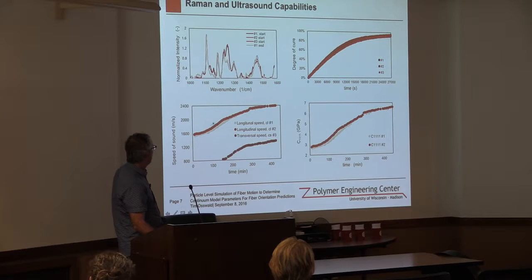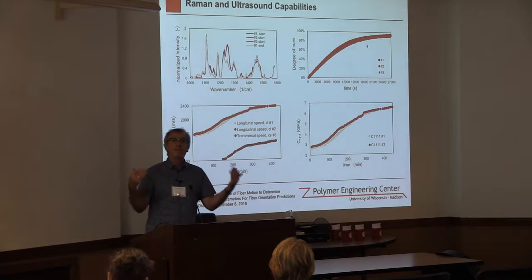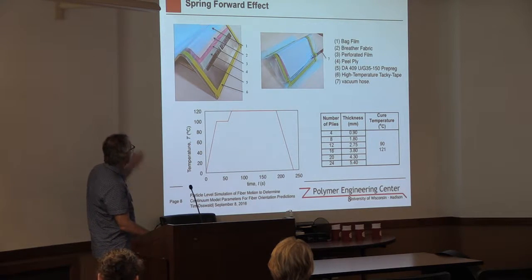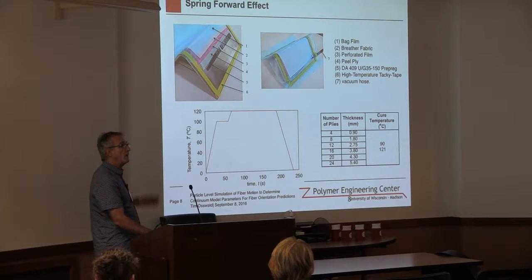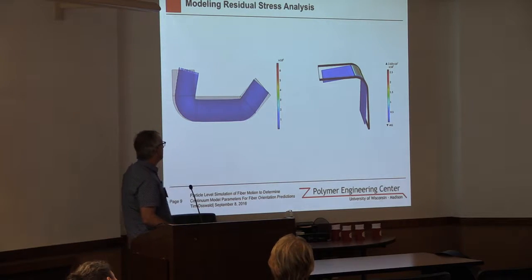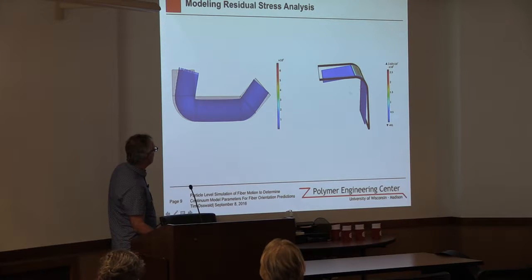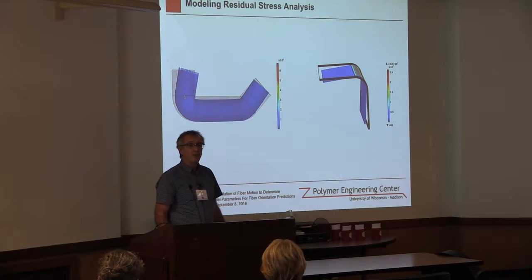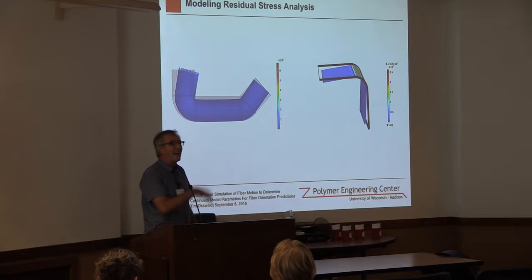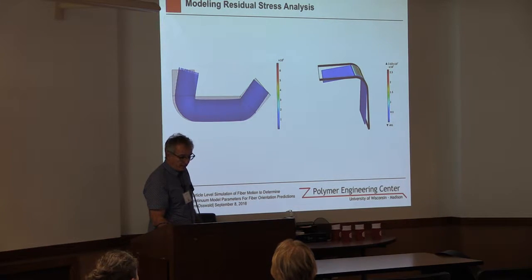On the other hand, the speed of sound also increases in time, so we can relate the modulus and the cure and find ways to predict that as the material cures. We need to know that for manufacturing complex structures — for example, an L-shaped structure that is a typical way of manufacturing parts for the aircraft industry. In this case it's an epoxy carbon fiber system. We then use the mechanical data as a function of cure to simulate and predict what spring-forward or warpage the part will exhibit during the process. So here we're matching measurements with simulation — not rheology, but rather curing and solid mechanics.